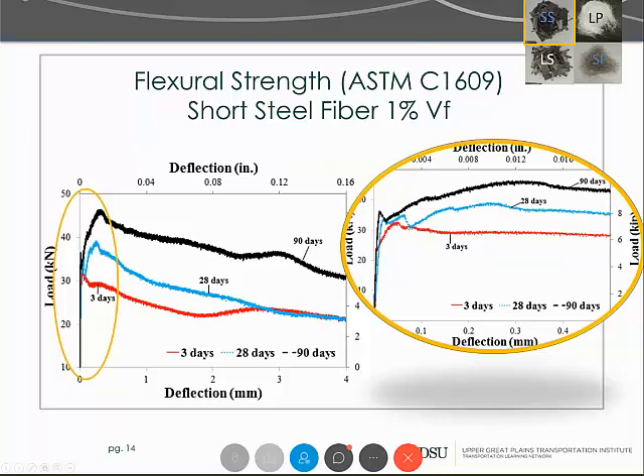So something like this I personally thought was really interesting, because this same fiber, the same concrete mix, if you tested it at an early age, meaning the concrete for whatever reason cracks at an early age, this fiber type is not as effective as if it cracked at like 90 days. So when it cracks at 90 days, the fiber gets more engaged, it can carry, it's tougher, it handles more energy, and it's not that the fiber changes or the concrete per se, it's just that the concrete gets harder, it bonds to the fiber, it has more time to bond and strengthen against the fiber, and it's actually forcing that fiber to go into a pulling mode as it breaks, it stretches the fiber more at a later age, and that's actually what the fiber is intended to do. We want it to stretch and to go into tension, because that's what fibers are good at. So at an earlier age, we just don't have much of a benefit.